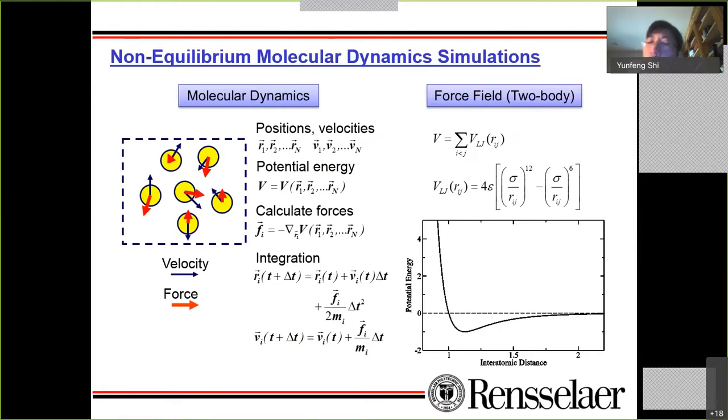It's called Lennard-Jones. So if you give every atom the position and the velocity, and you know their interactions through this analytical form, you will be able to calculate the acceleration. From that, you can do the integration and get the position and velocity of the next time step. You know the position at r(t), and now you know the position at r(t plus delta t). Delta t is called the time step. Then you do it again and again, and you will get a trajectory